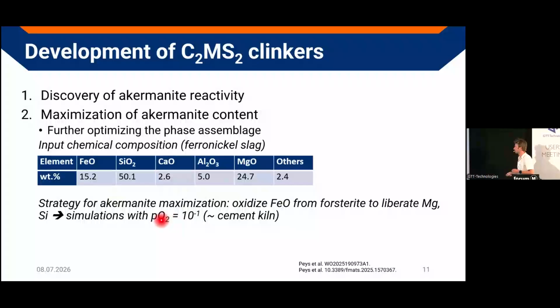We just put on, instead of a fixed composition, also a fixed oxygen content, we now fixed the PO2 of the simulations to something which looks like a cement kiln. And then we ended up with these simulations. With the calcium additions, your mass now drops because the CO2 goes out. And then you can see something quite similar happening as before, but now without this forsterite. Instead, we have a little bit of the magnetite, spinel magnetite.